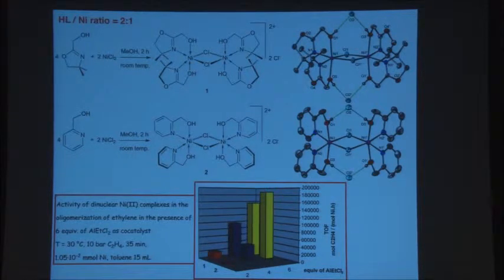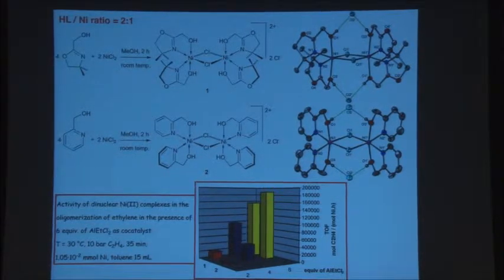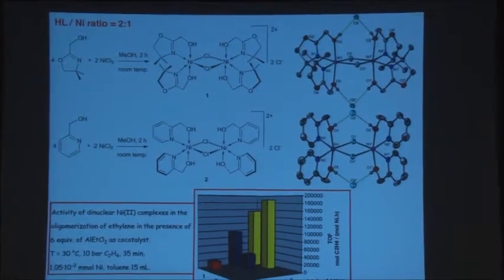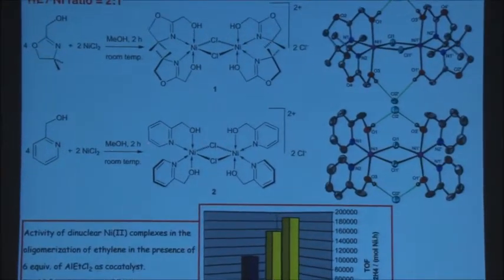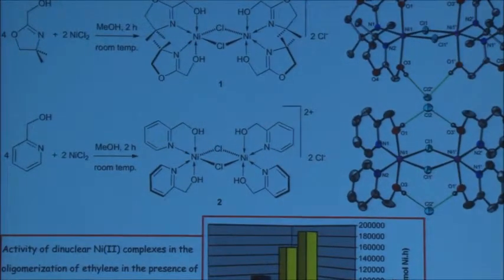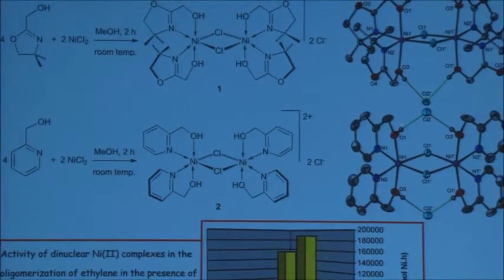For comparison, we thought it'd be interesting to take another heterocycle, which is well known, pyridine, which is now a nitrogen donor, but a 6-membered ring instead of oxazoline. We carried out a similar reaction, and you end up with a similar product and similar structure here.